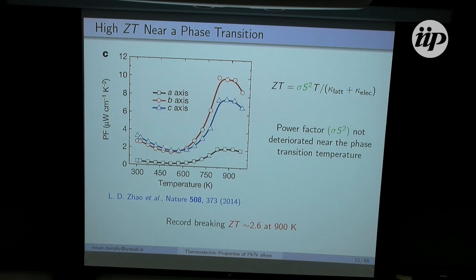So we have here the power factor of tin selenide, which, for anyone who doesn't know, is just the electrical conductivity times the Seebeck coefficient squared. Looking at this, in terms of thermoelectrics, these values maybe aren't anything to write home about, but if we look again near that phase transition temperature, it actually turns out that these values peak. I'm not going to claim that the phase transition is necessarily enhancing these properties, but it does show that as tin selenide undergoes the phase transition, these aren't negatively impacted. And this result, coupled with the low thermal conductivity you saw on the previous slide, gives rise to tin selenide's very high ZT of about 2.6 at 900 Kelvin.